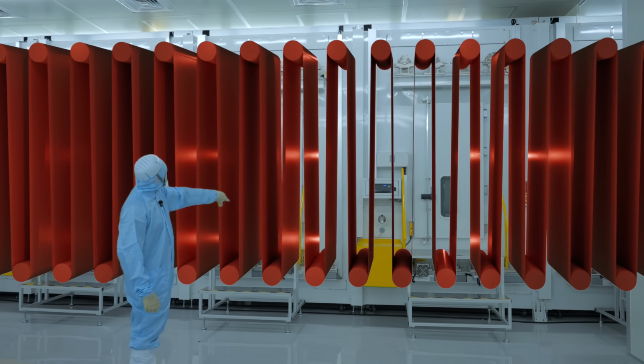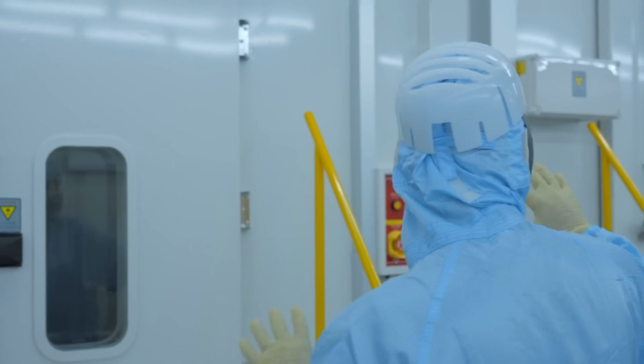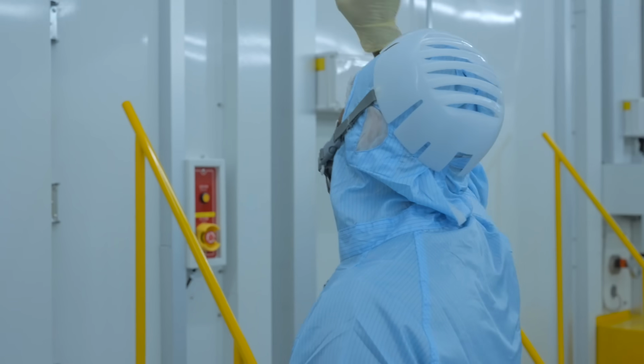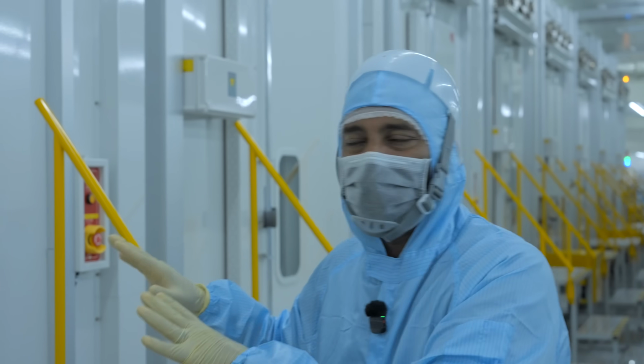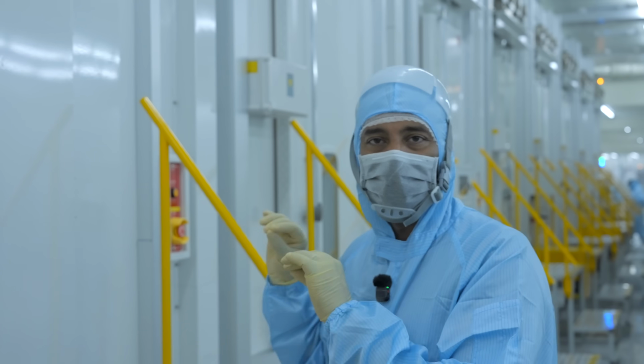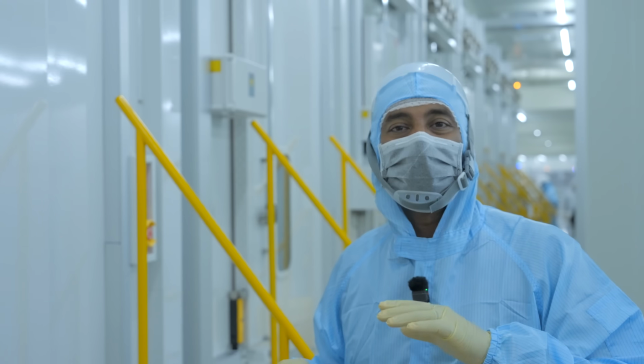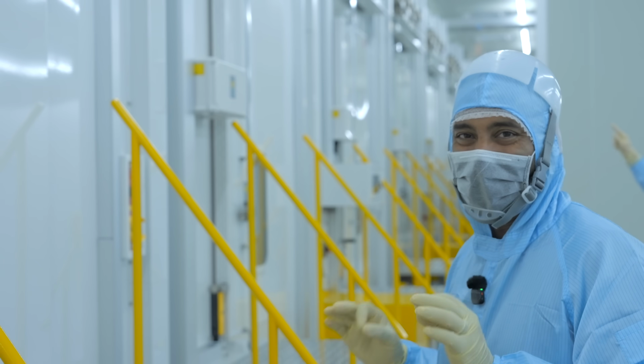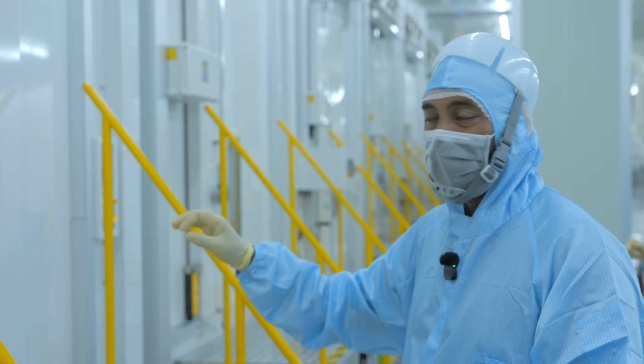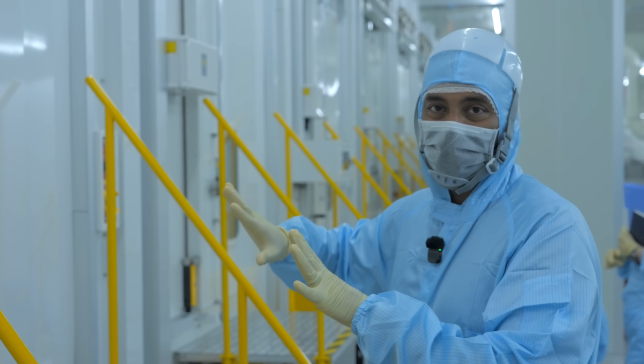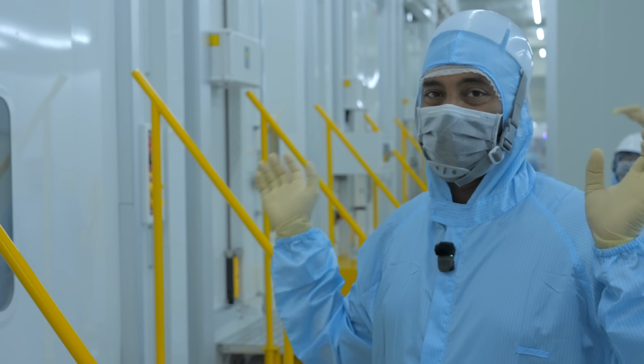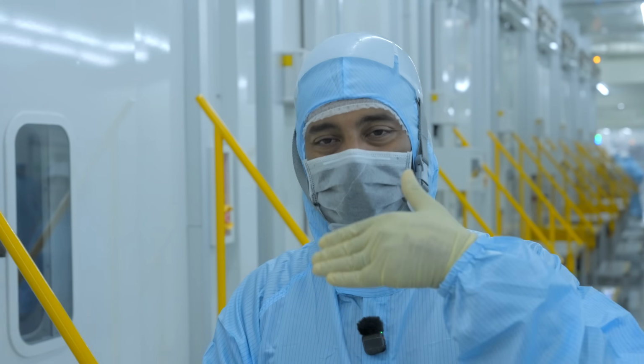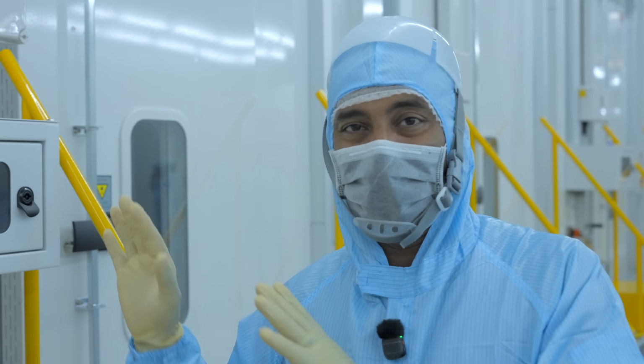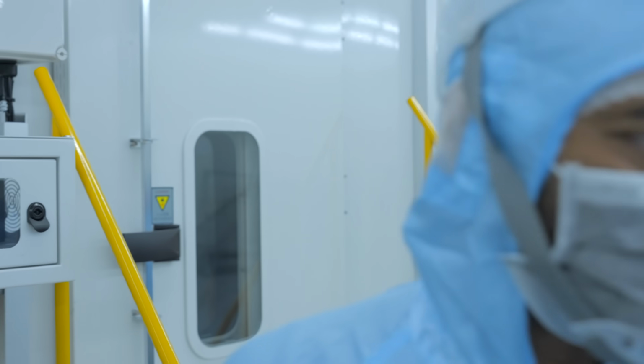This is that final drying stage. And because of this system, the speed that it goes through, and this orientation and some of the other secret sauce they have, they're able to get the humidity down in about 8 minutes, what normally takes most battery manufacturers 8 hours. And this is critical. At this point, when the roll comes out of this, there's no moisture because it's going into the dry room and continued all the way to assembly. So you can't have any moisture left after this step.